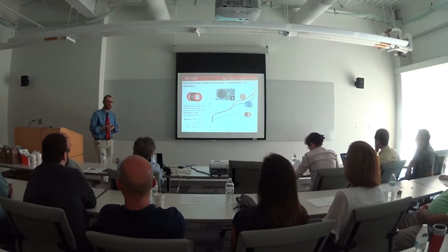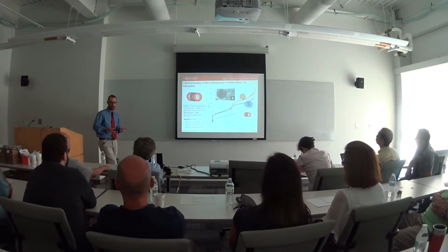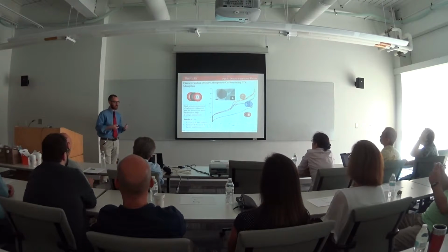So in this section of my dissertation, I used a different computational technique to look at a very special case of adsorption in specific materials called micromesoporous carbons. This is a picture of one particular micromesoporous carbon called CMK3. Typically, micromesoporous carbons are analyzed with either argon or nitrogen adsorption at cryogenic temperatures, which means 77 to 87 Kelvin, which is very cold. From these adsorption isotherms, we can derive a bunch of information about the pore size of our material using some methods which I'm about to talk to you about.